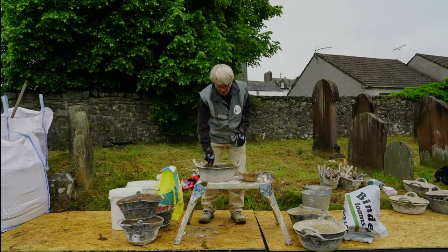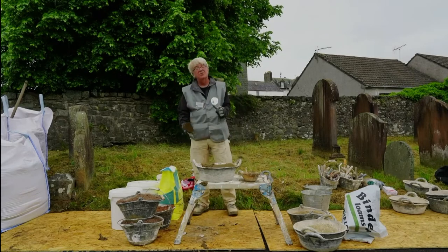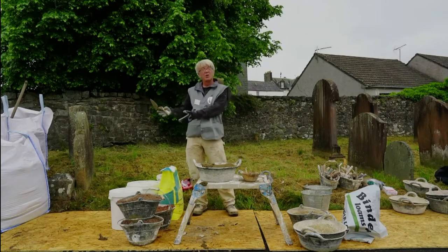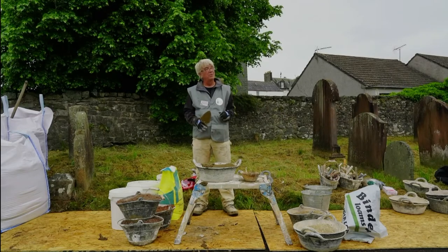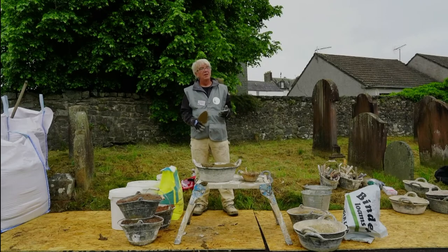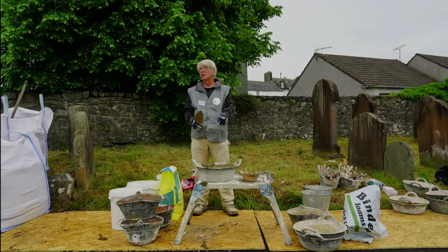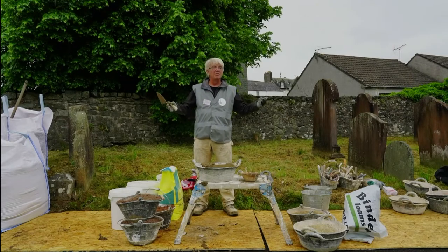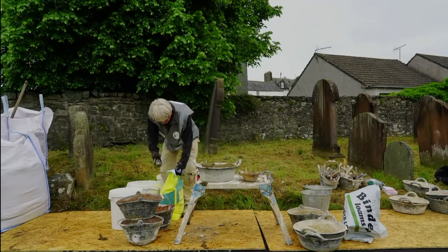So now I'm going to just put in a bit of lime, and that's the interesting thing here. It's quite a different story to the hot mixes where we have a load of lime. We don't need much lime to transform an earth mortar into something different. And of course, it's a stabilizer. That's one of its key roles. It stops that tendency for swell and shrinkage in the clay because it stabilizes the clay. So you'll hear lime stabilized soil. It does other things, but right.